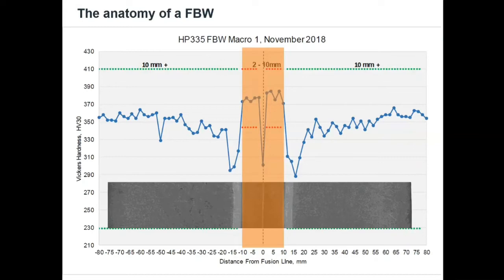What's happening after the weld, the predominant cooling mechanism is conduction. It's conducting heat away down the length of the rail, and the rate at which it conducts heat away is proportional to how much preheating you've done. So if you put a bigger reservoir of heat in the rail ends, you can slow that cooling rate and you can reduce this hardness. And we can play tunes with this by altering the parameters of the process. But it does accelerate cooling, akin to heat treatment, compared to the bulk rail hardness or the edges of the graph. So you do have an improved hardness on your air-cooled grades.